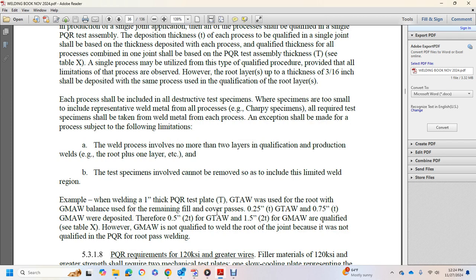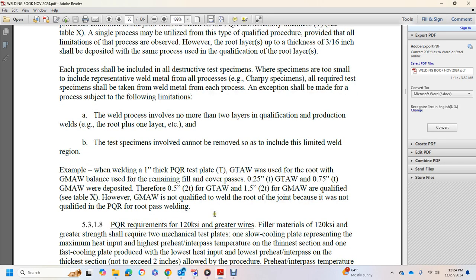For example, welding a 1-inch thick procedure qualification record test plate with gas tungsten arc welding, where you have the root welded with gas tungsten arc welding, gas metal arc welding for the remaining filler and cover passes of 1/4 inch and 3/4 inch, where the deposit thickness of 1/2 inch and 1.5 inch for gas metal arc welding is qualified. However, gas metal arc welding is not qualified for welding the root of the joint because it was not qualified with the procedure qualification record for the root welding pass.